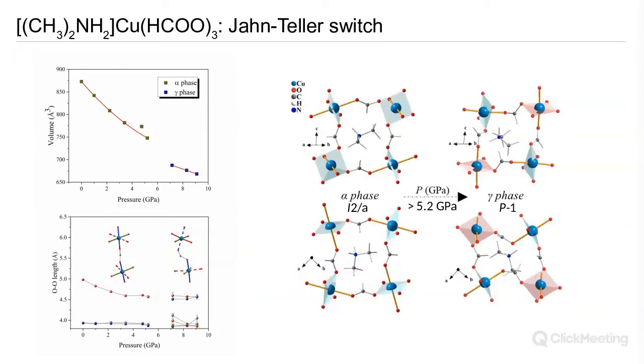of the copper sites, roughly speaking, maintained their orientation of the Jahn-Teller axis. The reconfiguration of the structure is quite severe, so I can't say exactly the same, but roughly, whereas 2 of them have rotated by 90 degrees, to good approximation. So we can consider this phase transition to be a Jahn-Teller switch, if you like, induced as a function of pressure, that, I stress, was not observed in the fully inorganic material system.